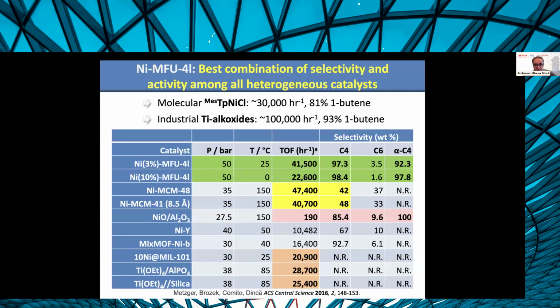catalyst for this reaction. Okay, it has turnover frequency that is competitive with the commercial catalyst, but it has much higher selectivity, close to 98.5% for 1-butene, with the balance being almost entirely hexene, so no polymerization whatsoever. And this is exactly what the industrial need for this reaction was.